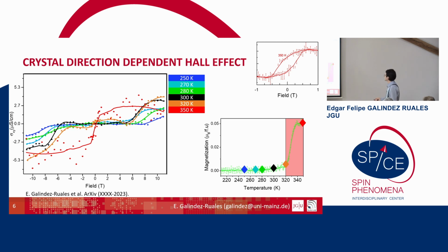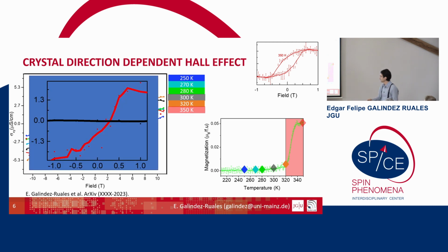So if we zoom in a little bit on the center, we will see that at room temperature we have no contribution at lower field, but at high temperature, in the easy axis phase of hematite, we have a jump that is the same size as the magnetic moment.